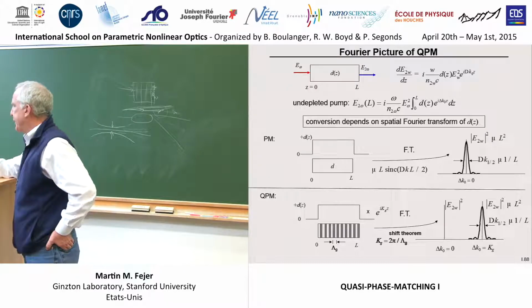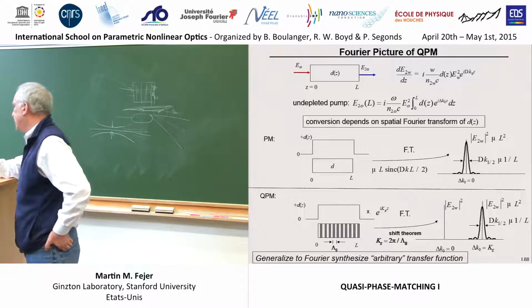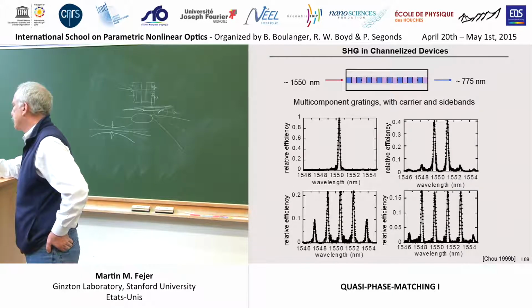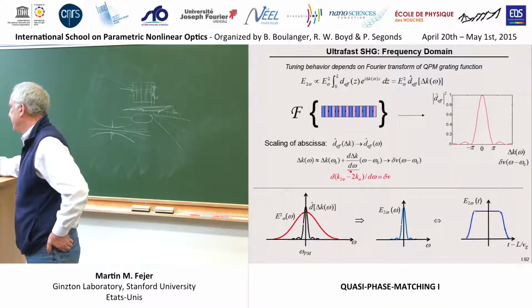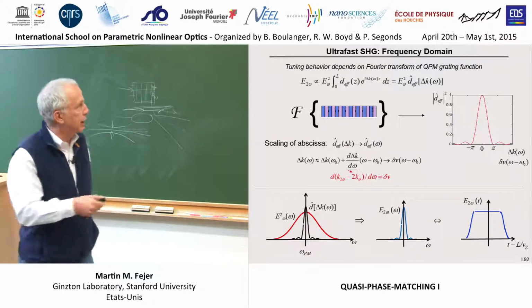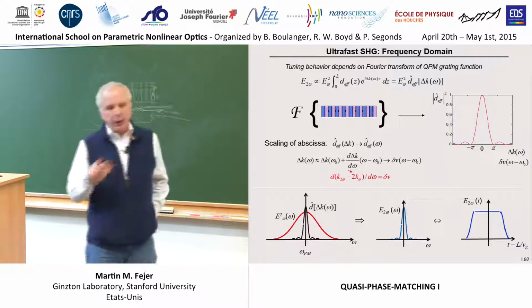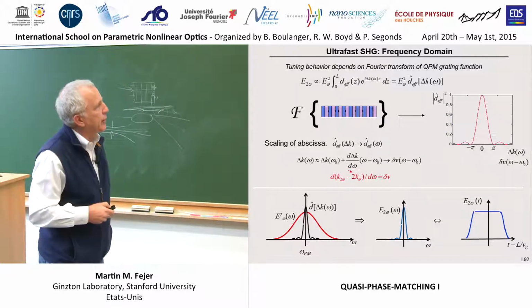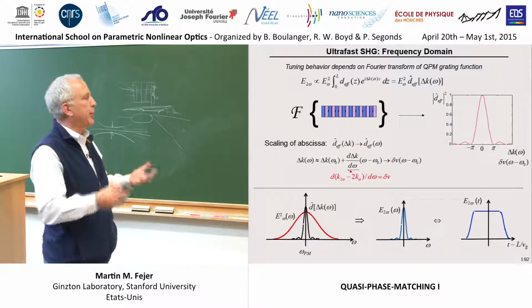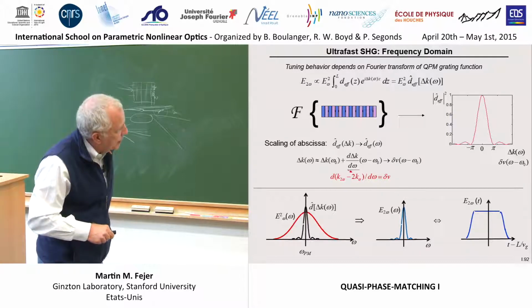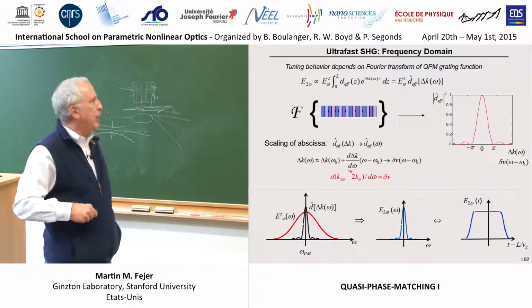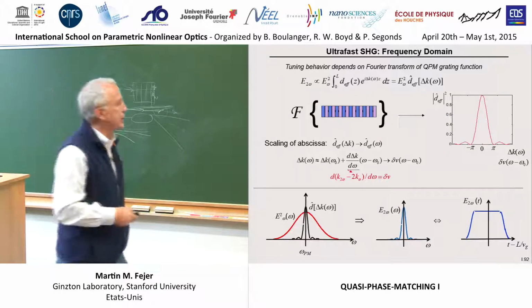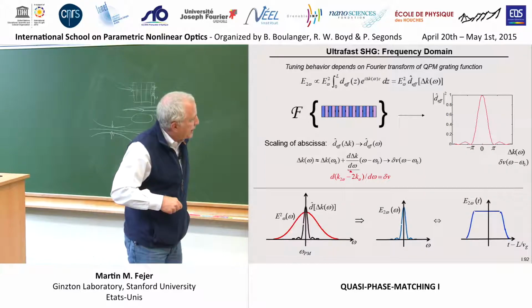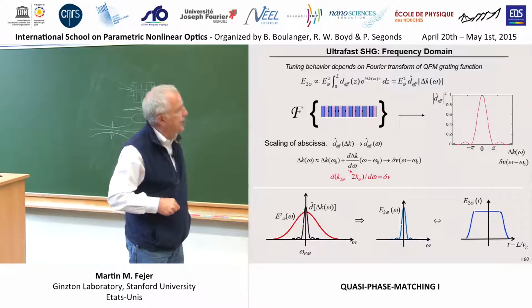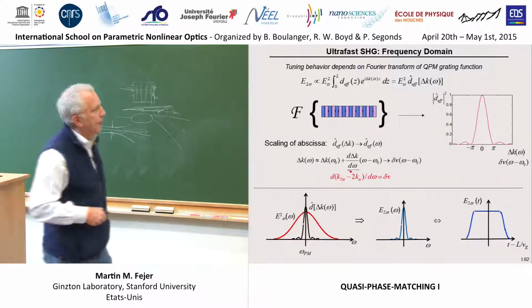So how would we look at that picture in the ultrafast domain? Well, now we don't have a monochromatic wave coming in. We've got a pulse. So the square of the pulse has a certain spectrum. And now how much harmonic generation efficiency each of these spectral components of the pulse sees depends on this sinc function, right? This sinc versus frequency, as we just calculated.